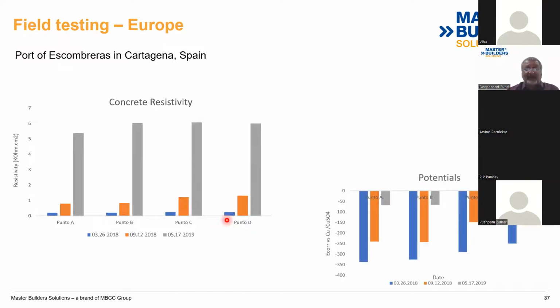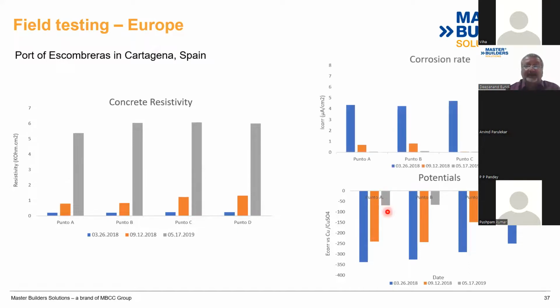The half cell potentials at the same locations, at point A, point B, C, and D, decrease. Over here you can see, and in terms of the corrosion rate, the ICOR values, as I said, in terms of microampere, they were almost coming to zero over a period of 1.5 years after the testing was carried out at all the 4 locations in this port. Now, mind why I'm saying port, because you can appreciate that these are very high corrosion exposed areas, and that's where you will have maximum chlorides getting deposited, and that's where the concrete needs the maximum protection. That's the reason we tested it over here.